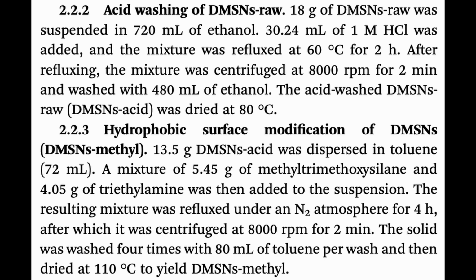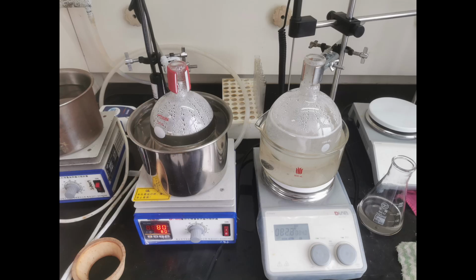However, before we load it with metal nanoparticle catalysts, the DMSNs-raw must undergo 2 further treatments to tune their specific properties, the first of which being an acid washing. Dilute hydrochloric acid is added to a suspension of DMSNs-raw and ethanol, and the mixture is heated at 60 degrees C for 2 hours before centrifuging, washing, and drying to give DMSNs-acid.